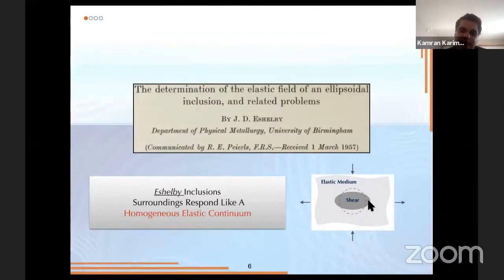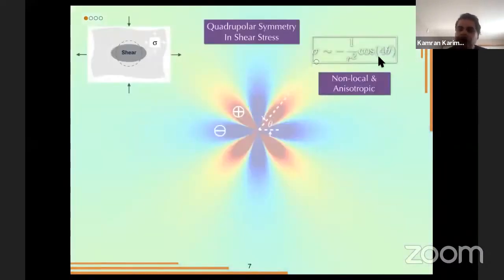So Eshelby solved this problem and gave this closed form solution for the spatial decay as well as the angular distribution of the stress. So 1/r² indicates that the stress perturbation is quite long range in space. This is a two-dimensional problem, and the exponent depends on the dimension. And you can see that there's fourfold symmetry. So here I'm showing the stress perturbation due to this shear transformation zone. Based on this form, we get positive lobes and negative lobes.